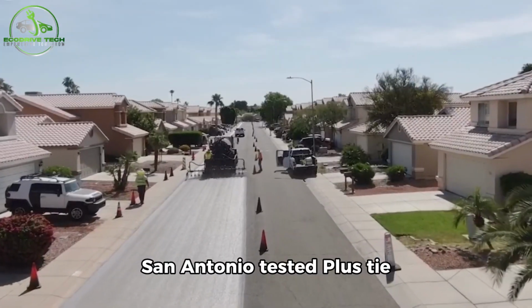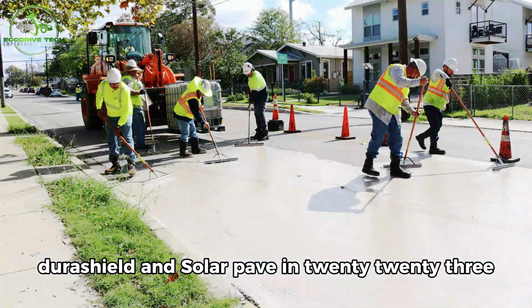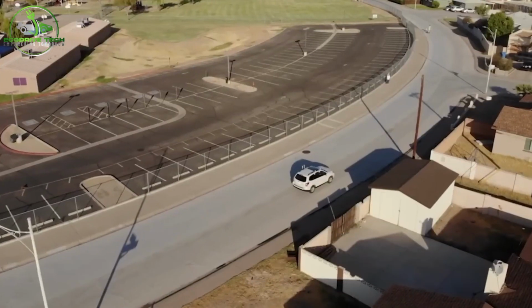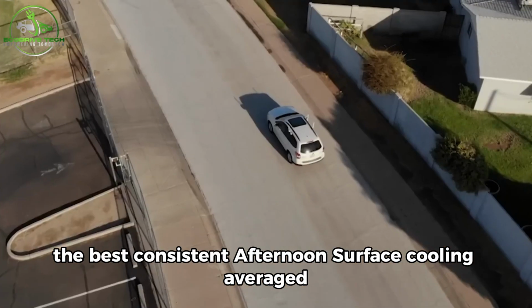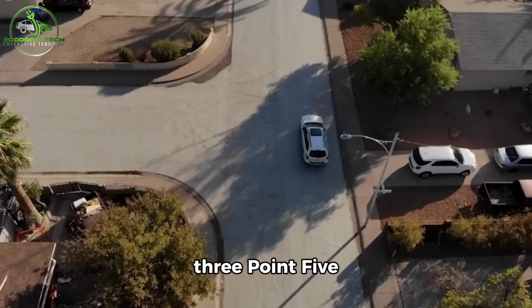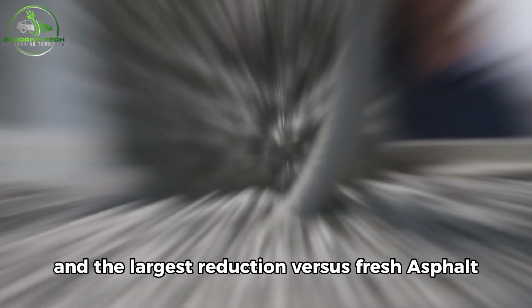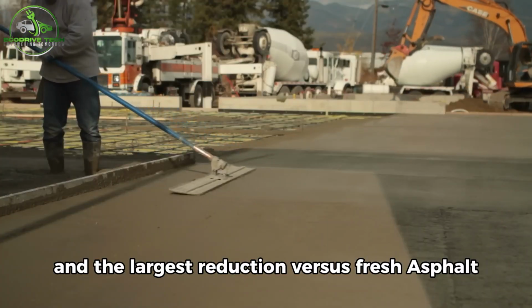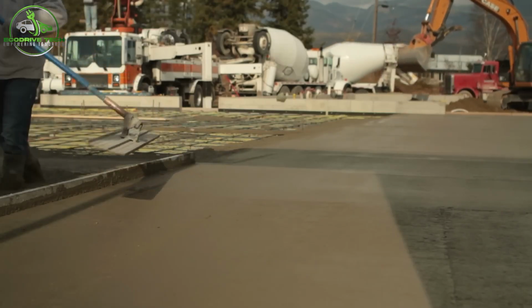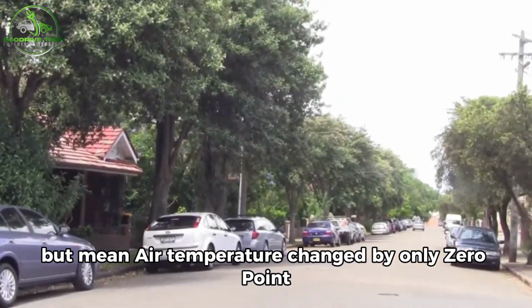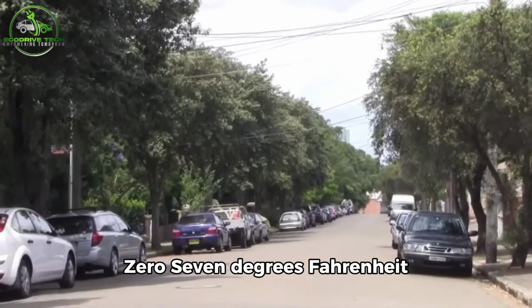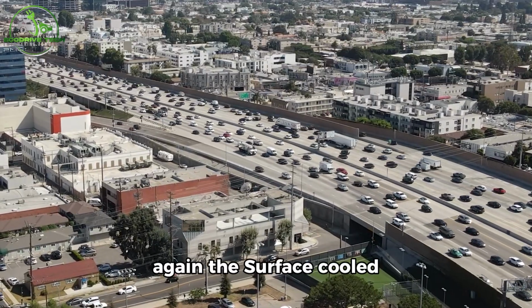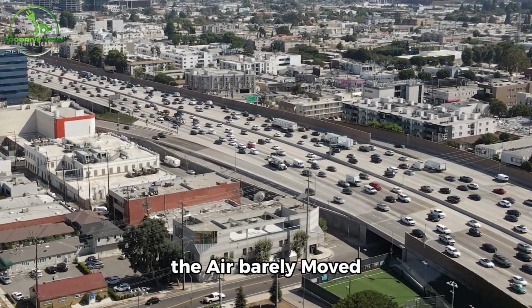San Antonio tested PlusTie, DuraShield, and SolarPave in 2023. The best consistent afternoon surface cooling averaged 3.58 degrees Fahrenheit, and the largest reduction versus fresh asphalt reached 18 degrees. But mean air temperature changed by only 0.07 degrees Fahrenheit. Again, the surface cooled. The air barely moved.